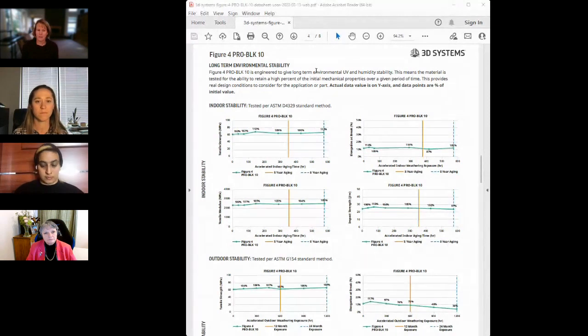So the indoor stability test is just UV and temperature, so constant UV exposure. And this test is a pretty well-established acceleration factor, so that about 600 hours is equivalent to 8 years in real life. And that would be indoors with light coming through a window. And you can see this material is quite stable under these conditions. We've got the strength, modulus, elongation, and impact strength here. They're all pretty flat across the whole 8-year span. So this material probably is a pretty good candidate if you're doing an indoor application.